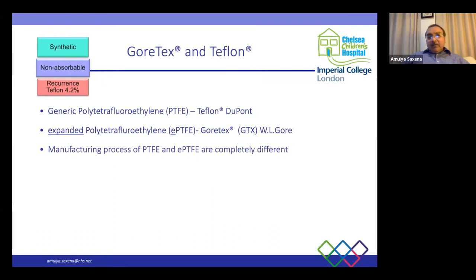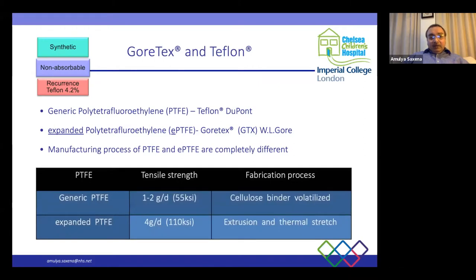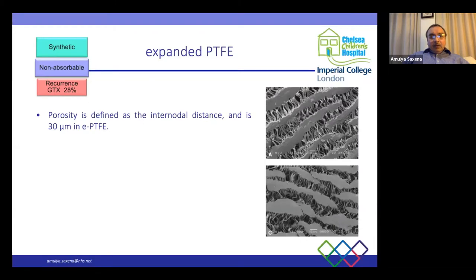The manufacturing processes of Gore-Tex and Teflon are completely different. It's not like this is also the same PTFE; one is expanded. As you can see, the expanded PTFE is made by an extrusion process, while generic PTFE is made with a cellulose binder and volatilization. I will concentrate more on Gore-Tex because that is the material that we use in present-day repairs. Now, looking at Gore-Tex, it's a synthetic material. It is non-absorbable. It has a recurrence rate of 28%.